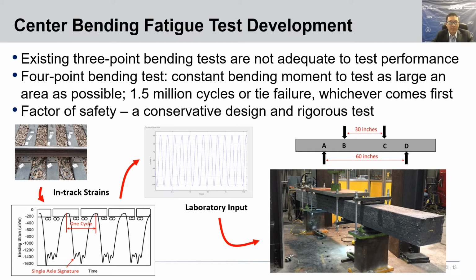Also considering the fact that most of the in-track center cracking failure was found within the middle 30 inches of the tie section, a 30-inch inner span setup was determined to be adequate for this test. In summary, based on the in-track strain measurement and several iterations to develop the test, a 4-point bending test setup is proposed, and the test runs for 1.5 million fatigue cycles or tie failure, whichever comes first.